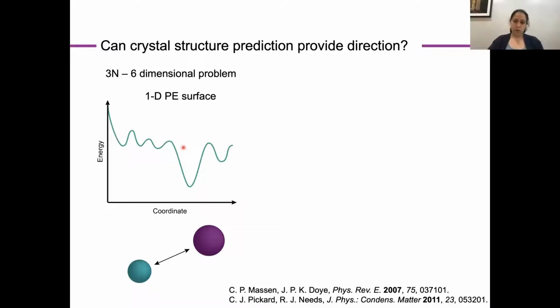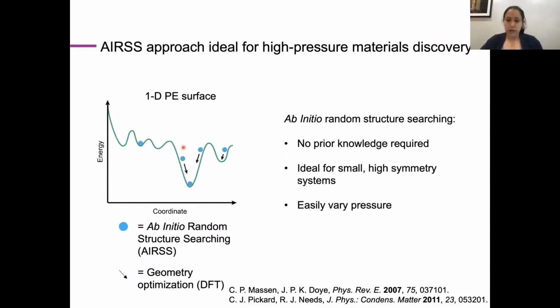In our case, we chose to use the ab initio random structure searching, or AIRSS approach, and we were mentored in the application of this approach by one of its founders, Chris Pickard, who has been very supportive in getting this research program in our group off the ground. And so in the AIRSS approach, what we are essentially doing is randomly assigning a random number of atoms to a randomly sized box. That's equivalent to dropping balls throughout our 1D potential energy surface.